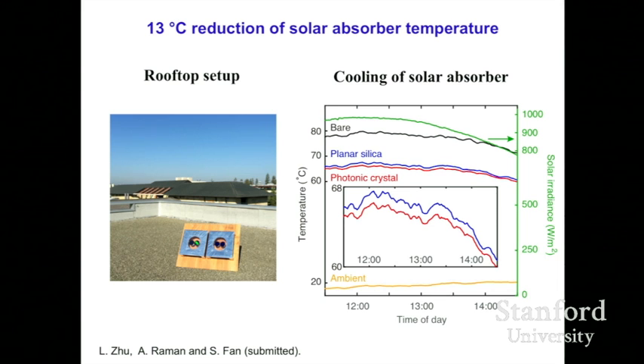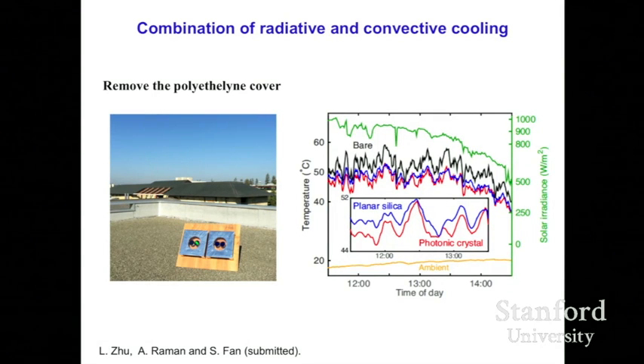So because the temperature is above the ambient, one can actually combine radiative cooling with convective cooling. And to do that, what we do is we simply remove the polyethylene film that covers the entrance of the box. As we do that, the temperature of all three structures drop because now you have convective cooling. But the photonic crystal structure still has consistently lower temperature compared with the bare sample as well as the planar silica sample. And this again indicates the possibility of using radiative cooling together with more conventional cooling mechanism for solar cell in order to lower the temperature of the solar cell.